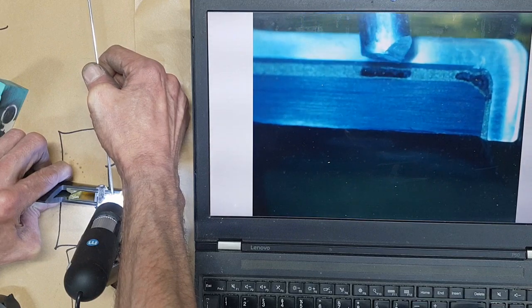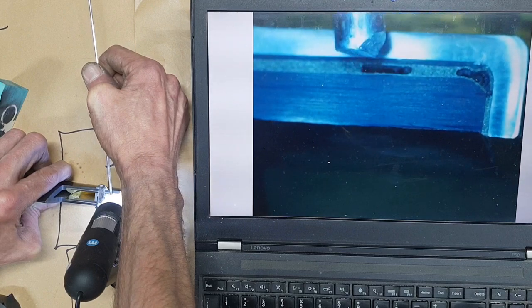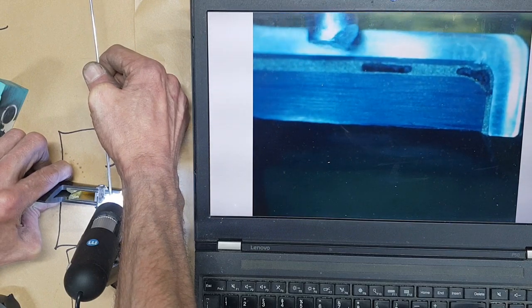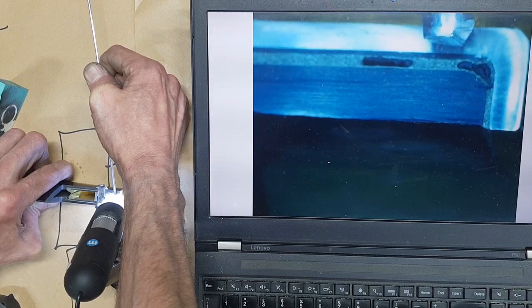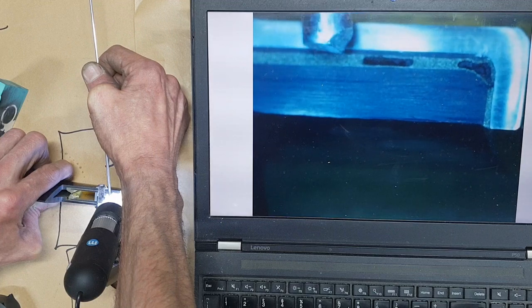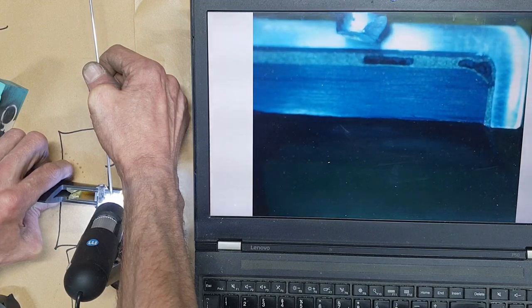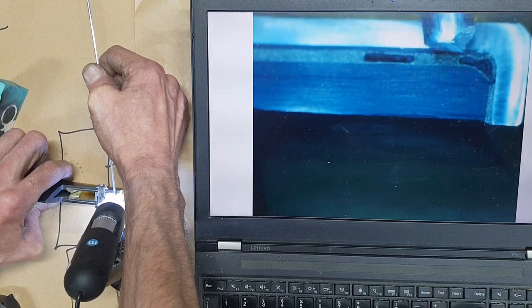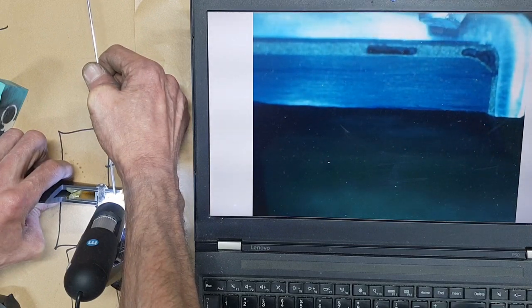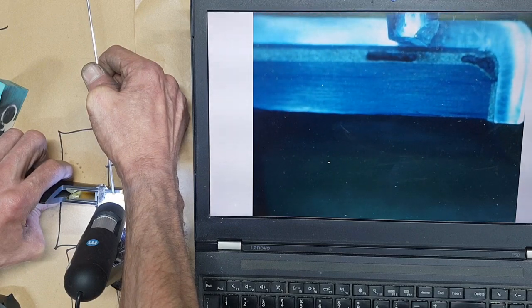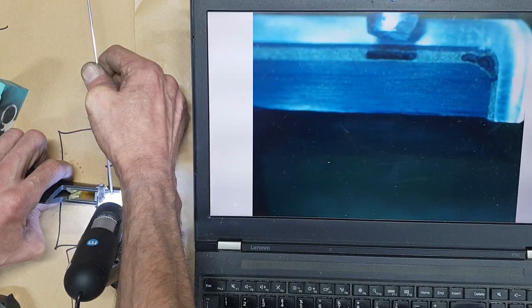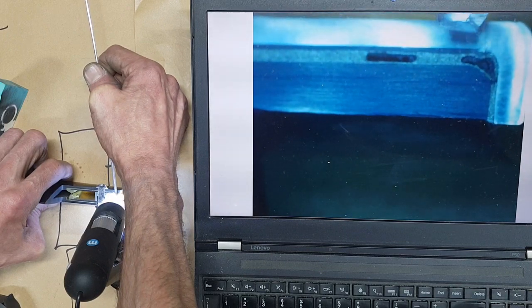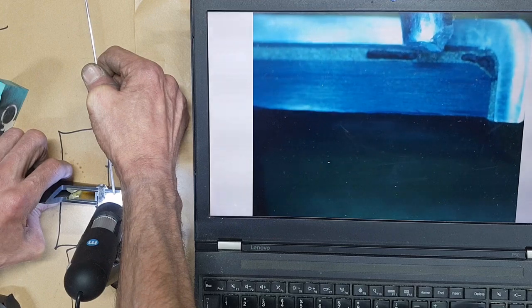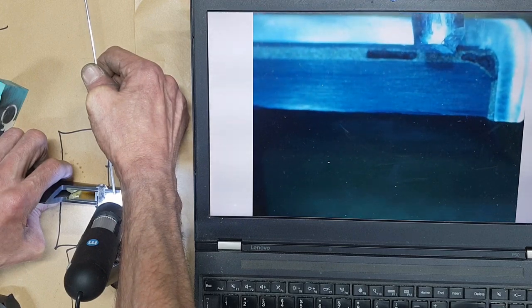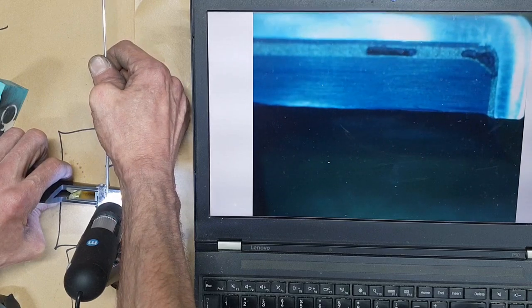They then sand that part with the epoxy on it. So the epoxy creates its own atmosphere, which shields it from oxygen, which stops the part from oxidizing, and you get a proper bond line. So this part would have been, first of all, sandblasted, coated with epoxy, sanded, which prevents the oxygen getting at it, and then you've got a proper bond line, so you can bond again, secondary bond, when you're putting it into the part. Now this is pretty hard to show and describe because it's just so small, but hopefully you get the idea.